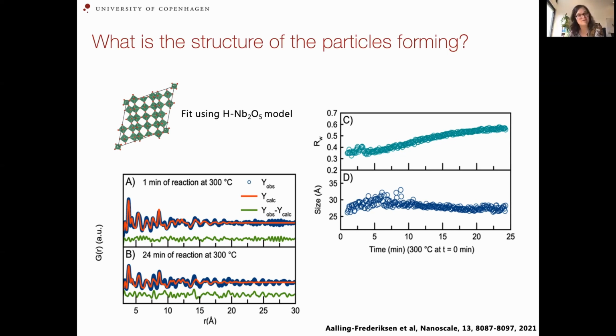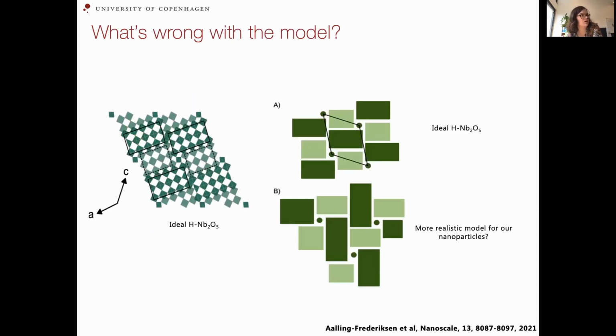But after the nanoparticles have grown a little bit, we don't fit all of this that is out in the PDF. So that shows that the H-Nb2O5 model is a bad model to describe the particles that we have here after 24 minutes. We can also see this, and this is a little bit more technical, in the fit quality, that it really doesn't fit. So we were thinking about what else to do.